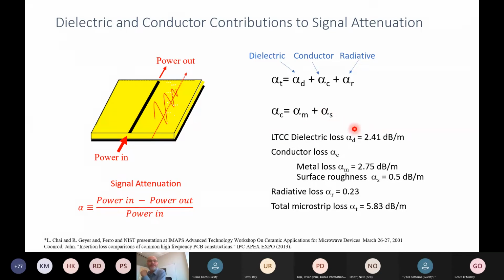And so we can then do some accounting, add all these up to figure out their contributions to the total loss of the microstrip. As you can see here, radiation losses, at least in this frequency range, sub 10 gigahertz I believe, were pretty low. But we can see here, at least for this dielectric and metal, we had pretty much equal partitioning of the contributions of the loss of the metal and the dielectric, so both contribute.